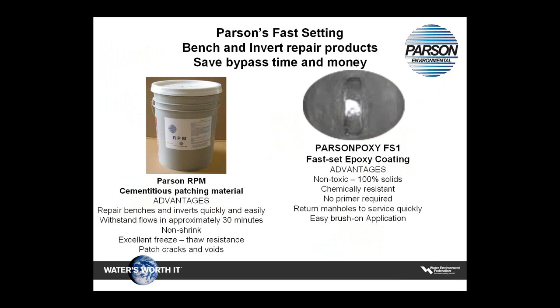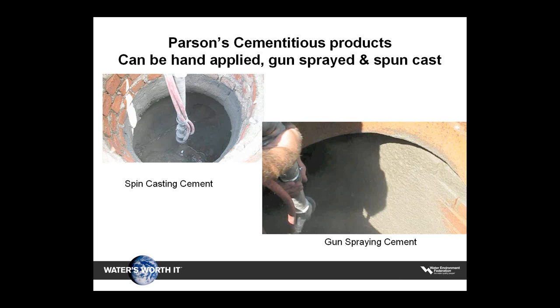Some rehabilitation projects could require repairs to the manhole bench and invert. The repair products need to be easy to apply and set up quickly. Parson RPM is a cementitious product that has a set time of about 30 minutes. It can be used for repairing the invert or patching the bench, as well as other areas in the manhole. Parsonpoxy FS1 is an epoxy coating that is 100% solids, can be brushed onto the invert or bench, and has a set time of about 45 minutes.